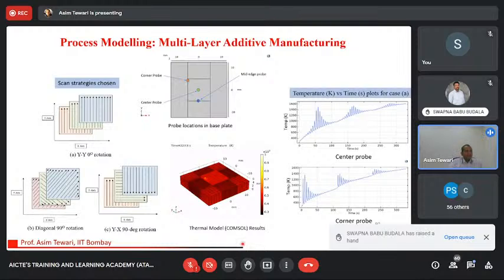Now, the other part which I talked about, which was the porosity. So I want to now quickly talk about, so there were two major aspects which I said additive manufacturing have an issue. One is distortions and residual stresses and cracking, all because of residual stresses. The second is porosity and the microstructure. So I want to quickly talk about some aspects of the complexities which you can get in a microstructure. And what you need to realize is that when you are going through a process of welding, your microstructure really goes through a very, very complex process of, let me just try and see if I can pull that for you so that you can appreciate as to what is happening in your welding microstructure and what is happening in your additively manufactured microstructure.